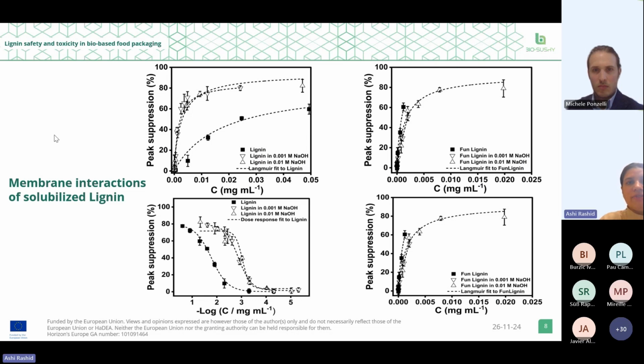In case of the unfunctionalized lignin, in the presence of sodium hydroxide, the membrane interactions increase significantly compared to the membrane interaction in the absence of sodium hydroxide. Sodium hydroxide has been reported to depolymerize the lignin into lignin derivatives. So sodium hydroxide here has not only enhanced the solubility of the lignin, but also hydrolyzed the lignin molecules into different lignin derivatives and oligomers, which presumably have interacted more strongly with the biomembrane sensor compared to the lignin itself in polymeric form.